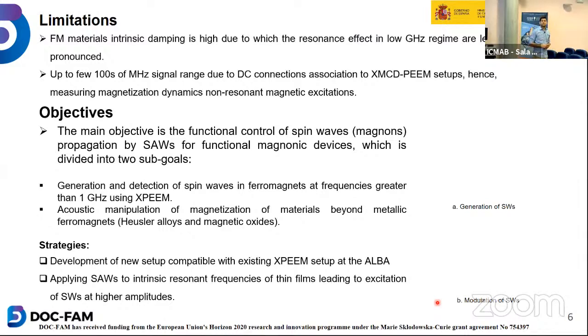For that, I proposed two strategies. As I told you, with the XPEEM it was not possible to reach more than 2 gigahertz into the gigahertz regime. So we had to design a setup which can reach higher magnetic fields and higher frequencies, and then apply SAW. We applied SAW with frequencies that are the intrinsic resonant frequencies of the material.